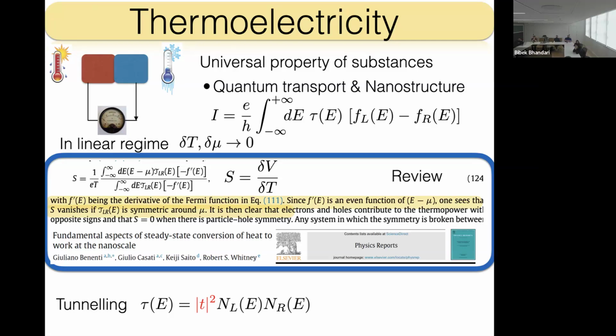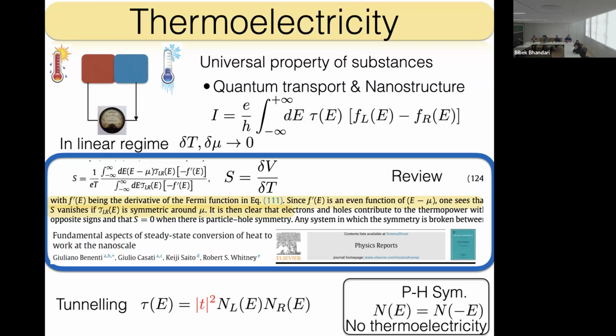And now if you have a superconductor, you have this symmetry that is called improperly particle-hole symmetry, okay? And due to symmetry, you are lost because you cannot have thermoelectric effect at the linear level. This is the point. And it's true also for metals, right? It's roughly true also for metal. Indeed, the effect is very small because this is true also for metal around the chemical potential, neglecting order of T over T_F. So because you need to have a little bit of curvature of your spectrum.